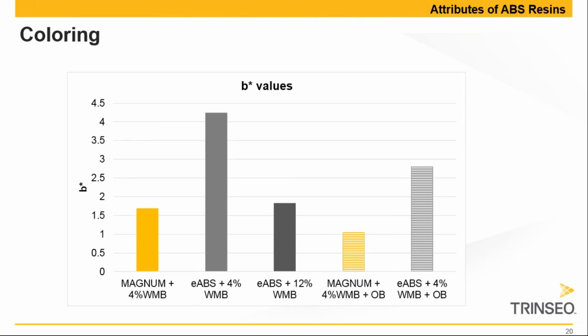This graph shows a similar picture, but now I've added 2 experiments. We have added a fixed amount of optical brightener. With an optical brightener, you can give your sample a brighter and a lighter appearance. But even with adding an optical brightener, the message is the same. It is even so that the Emulsion ABS with 4% master batch with optical brightener still has a higher B star value than the Magnum with 4% master batch without optical brightener.